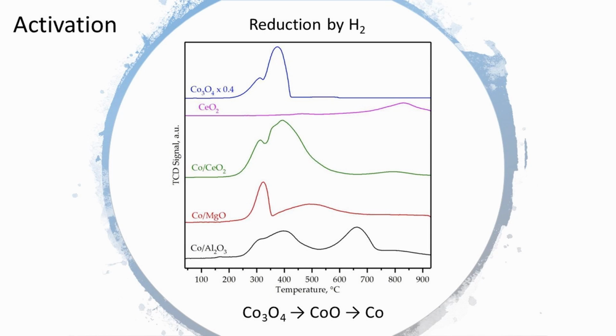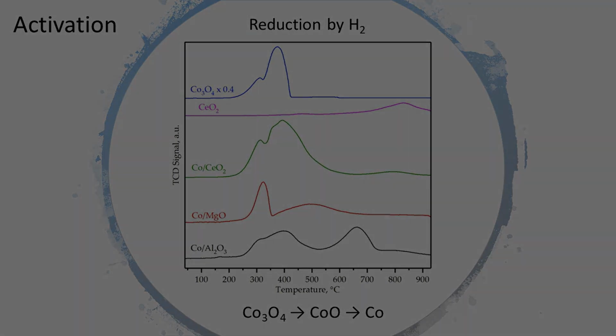In particular, the two-step reduction of Co3O4 to CoO and to metallic cobalt is relevant in this respect. Usually the first step is facile, but the second step is slow because of the strong interaction, through mixed compound formation, between CoO and the support.